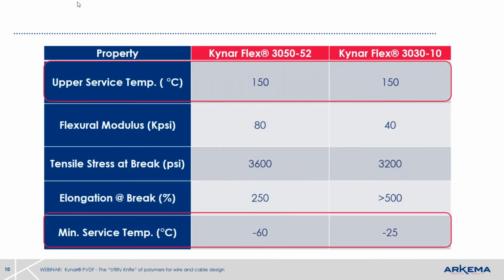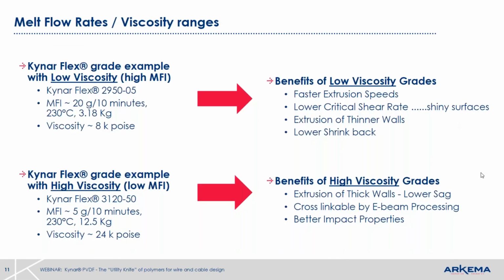For low temperature properties, we get this question all the time, which are the best grades for low temperature? The absolute best material that will take a low temperature impact is this grade, Kynar 3050. This grade will withstand a cold temperature impact to -60. We have another grade, 3030, that will take an impact to -25. So these are not manual tests, these are physical impact tests. So if you have a low temperature application, these are the grades you may want to consider.